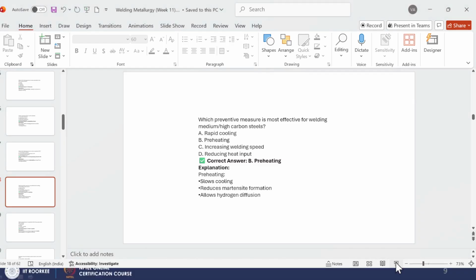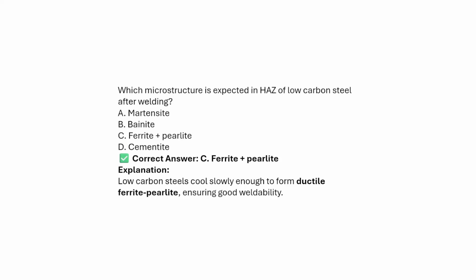So next, which microstructure is expected in the HAZ of low carbon steel after welding? A, martensitic phase; B, bainitic phase; C, ferrite plus pearlite; D, cementite. In the case of low carbon steel, there is less hardenability, even in the HAZ. The most probable answer is option C, ferrite plus pearlite. In low carbon steel, the cooling is slow enough to form the ductile ferrite and pearlite phase, ensuring good weldability.